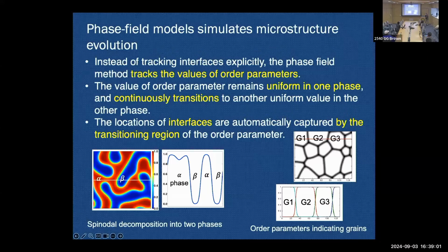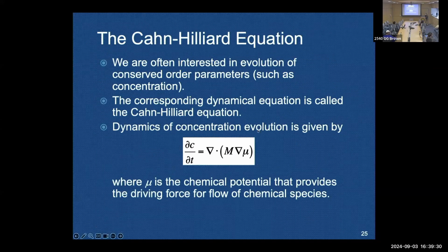You can apply it for a conserved order parameter, something like concentration, or for things like orientation, which doesn't need to be conserved. So this would be like a polycrystalline material, and the order parameter for each one of those grains is 1 within that grain and then 0 outside. And the equation for the phase field model for conserved order parameters is really a statement of mass conservation.